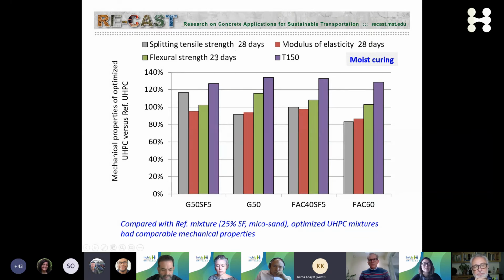Here we have splitting tensile strengths, flexural strengths, elastic modulus, and the last one is the ductility. So very similar, 100% or above. This one is, we pushed it a lot with fly ash. Some of the US states don't have slag or silica fume, so we do have to use some fly ash.